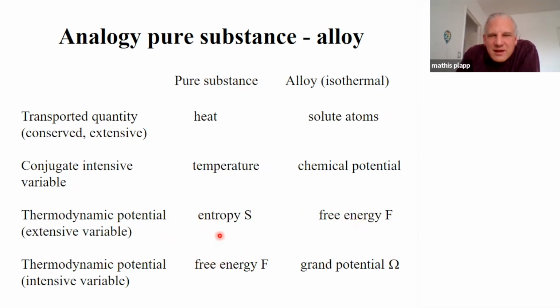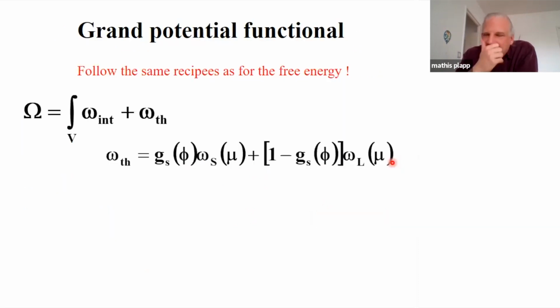And in the alloy case, well, the extensive variable here is the solute concentration. So for this, the appropriate thermodynamic potential is indeed the free energy. But if you want to use the intensive variable that would be analogous to the temperature, then you should not use the free energy, you should use the grand potential. Okay. And for me, I think it's quite obvious why people wrote from the start phase field models for pure substances in temperature and for alloys in composition, because those are the two things that you can easily measure. But thermodynamically, they are not equivalent. The equivalent of the temperature is the chemical potential and not the composition. Okay, so let's see how this goes.